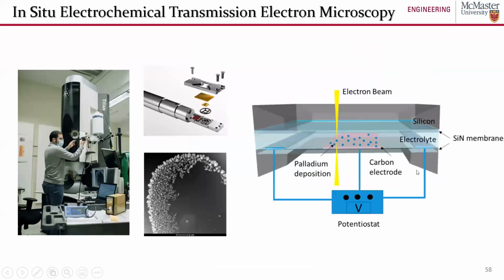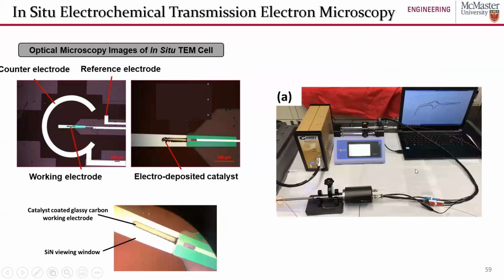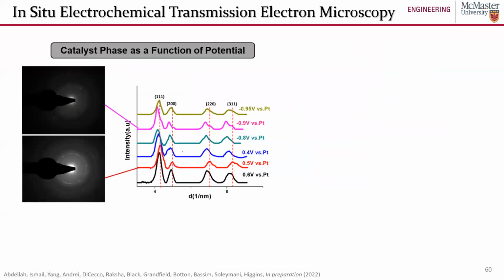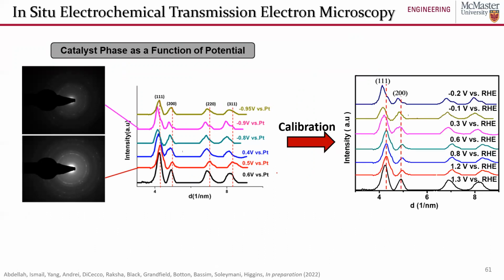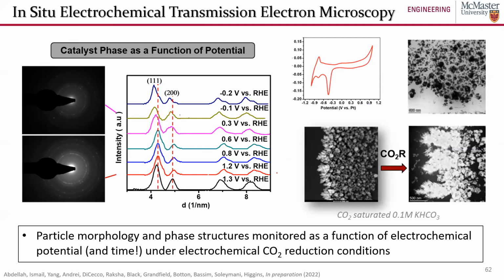Then, okay, I'm pretty much out of time. I was going to show some results of in situ TEM, but essentially what we're able to do is track the crystal structure or phase of materials as a function of potential, as well as the structure of these materials as a function of potential. Ahmed Abdallah, a PhD student in my group, did these measurements. Initially he did these measurements versus the platinum quasi-reference electrode he was using. But as a good electrochemist, he did his calibration. He switched them all to RHE scales, and we're able to show the phase structure of these materials as well as the morphology of these materials as a function of potential.